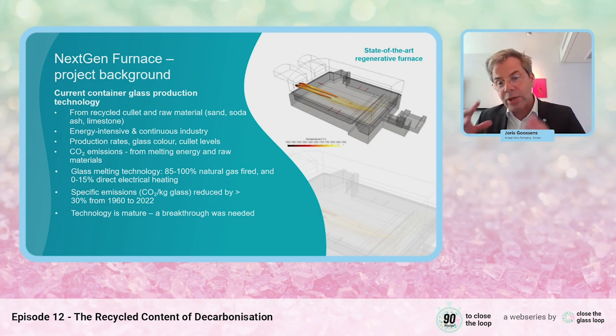So the entire glass community has worked to reduce the specific emissions, and in the last decades this has decreased tremendously. But we are reaching, let's say, the thermodynamical plateau, where further improvements are very tough and nearly impossible, because we reach this thermodynamical limit. And that's where a breakthrough is needed, both because the technology is mature, and also because we are closing in on 2050, which is less than 2 furnace lifetimes away.